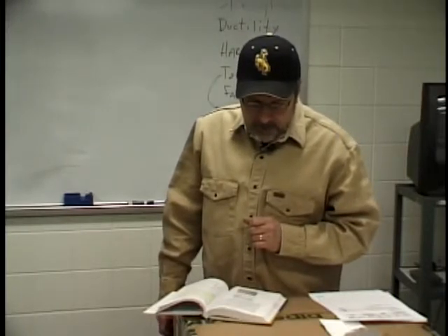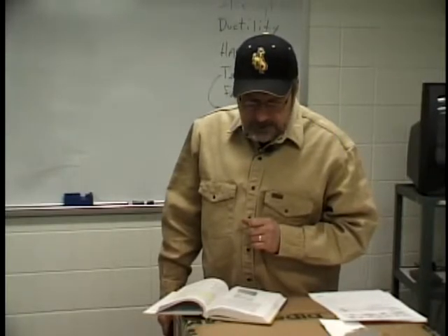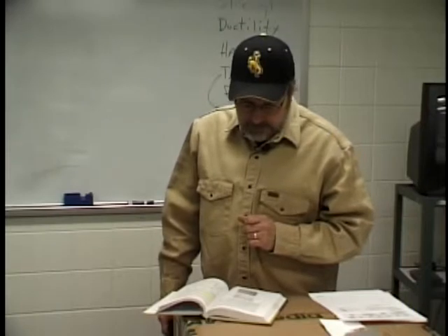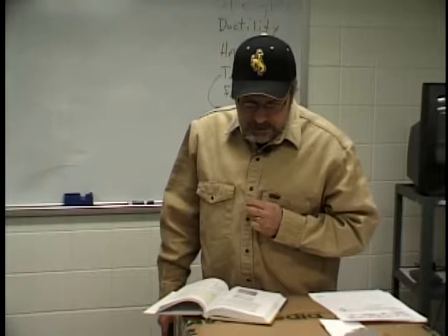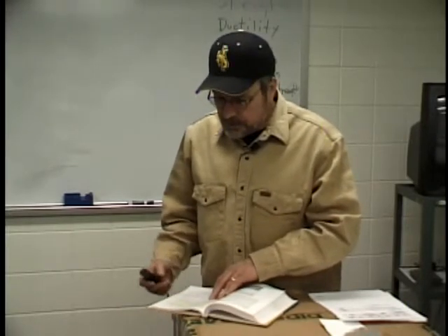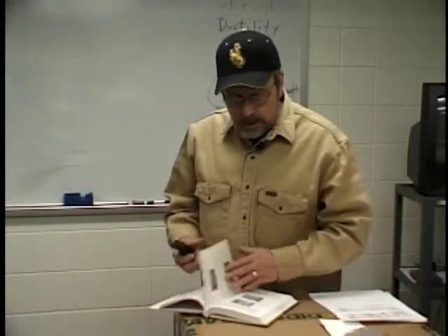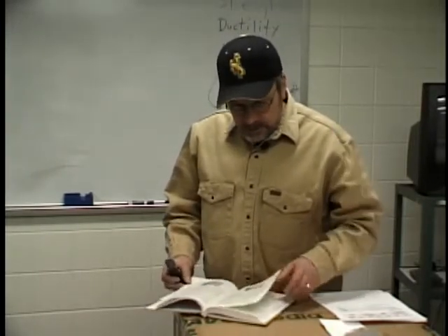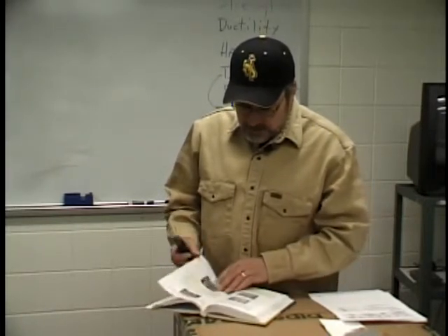Bainite is another structure that can occur in steel. It may have either a feathery or acicular appearance, that's that needle-like. Bainite is produced by quenching steel from an elevated temperature to a temperature above about 400 degrees Fahrenheit, depending on the composition of the steel, and holding the steel at this temperature for a long time. It does not normally occur as a result of welding. Ones I would like you to remember here would be ferrite, cementite, pearlite, martensite, and Widmanstätten structure.